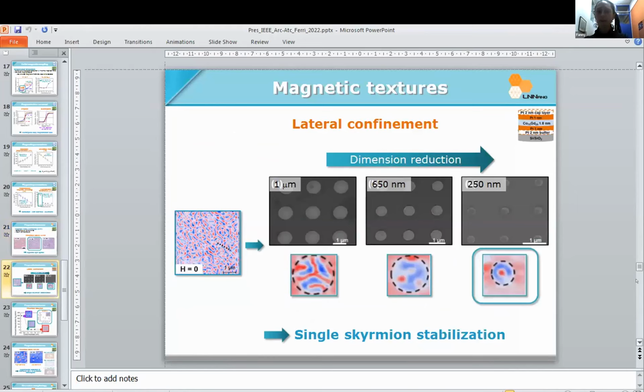But now if we do lateral confinement, on the left you have the unpatterned film with spin spirals, and then patterning from disks of 1 micrometer down to 250 nanometers. You can see below, in the electron microscopy image, that for one single nanodisk at 1 micrometer diameter you still have a spin spiral, but reducing to 650 nanometers you already have some skyrmions, three skyrmions here, and then at 250 nanometers you have one skyrmion in the middle of each nano island. So by doing this lateral confinement, we were able to stabilize single skyrmions, even in a host that normally is in a spin spiral region.